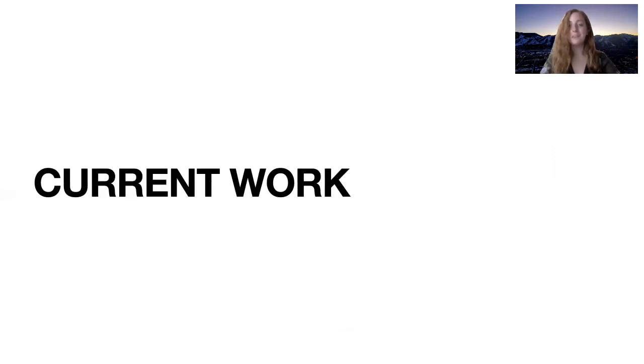So what are we currently working on? So present work as of January 2021, we're currently working with an alloy, which I'm not allowed to discuss because it's unpublished, but we're having some success with this alloy. But we have a processing route for how we want to mechanically test it. So first we're trying to arc melt the button, and then we're going to stress relieve it at 850 degrees Celsius for an hour. And then we're going to use the 240 grit paper to do some oxide removal, then cold roll it, and then use a water jet cut and anneal at 850 degrees Celsius for 2 hours, and then do some fine grinding, and then finally we'll do a tensile test, which you can see on the right-hand side of the screen. That's an example of what we're going to be doing.